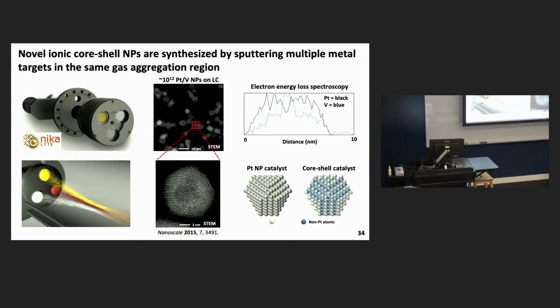And when you're done, you end up with something like this in the STEM, where the Z contrast is higher in the shell than it is in the core. And that indicated that the platinum might be in the shell. But of course, you have that issue of greater thickness when you look along the side, right? So we wanted to be sure, and we went in and did electron energy loss spectroscopy. And this allowed us to confirm that, yes, the platinum is in the shell, whereas the vanadium is located primarily in the core. So we think we generated something like this, right, that theoreticians are interested in.